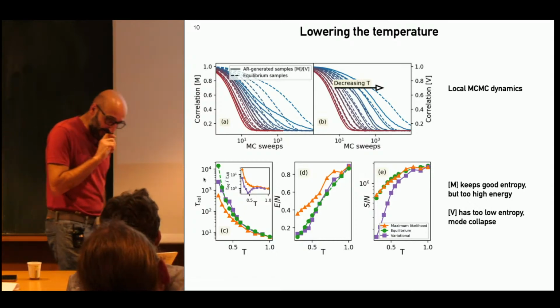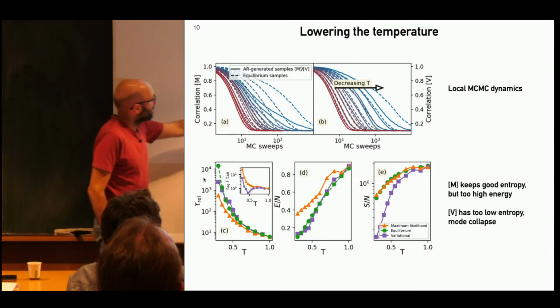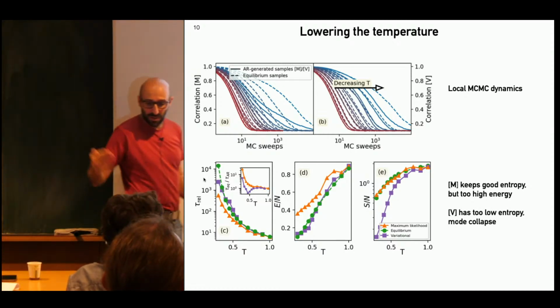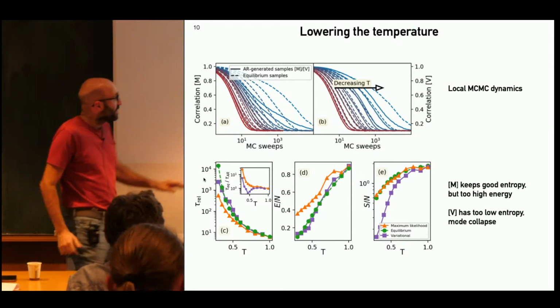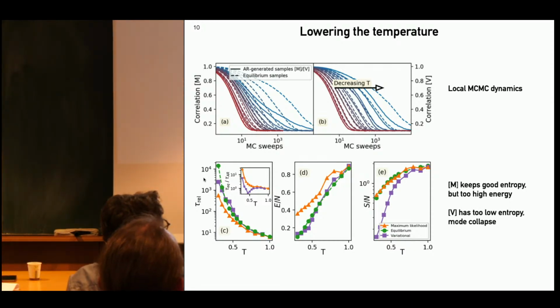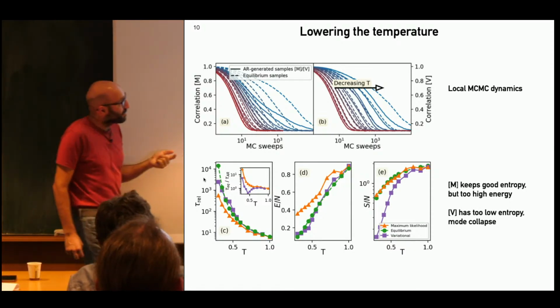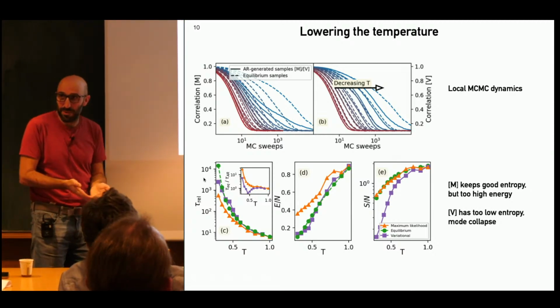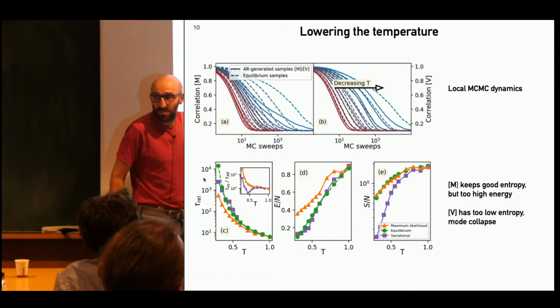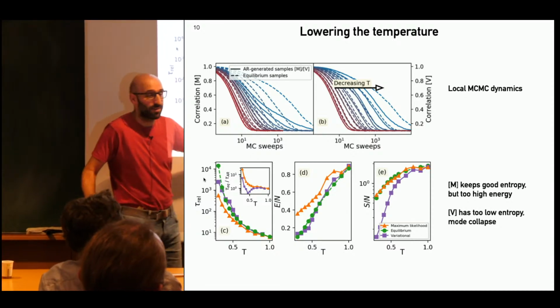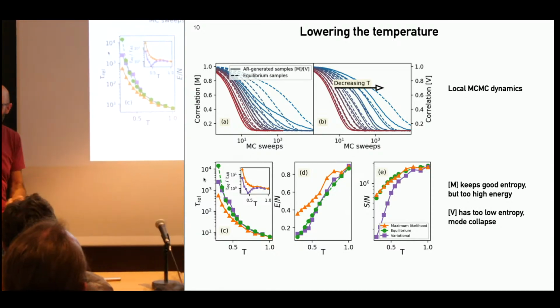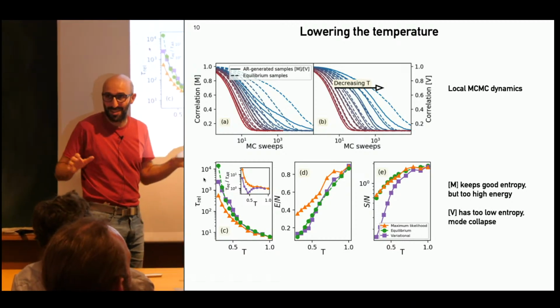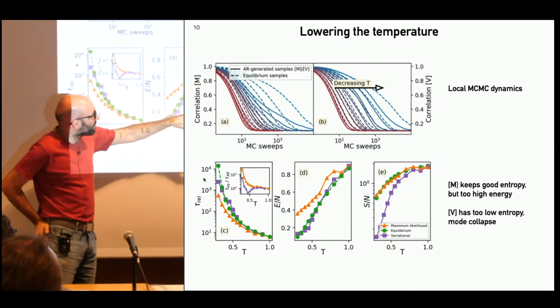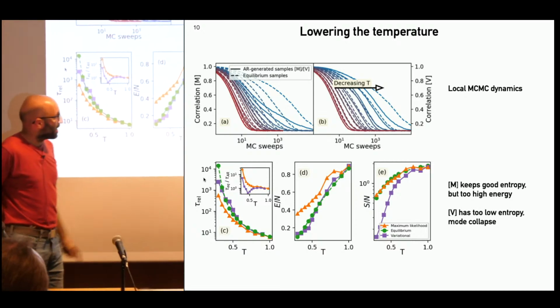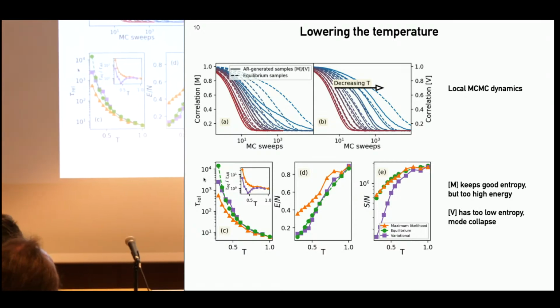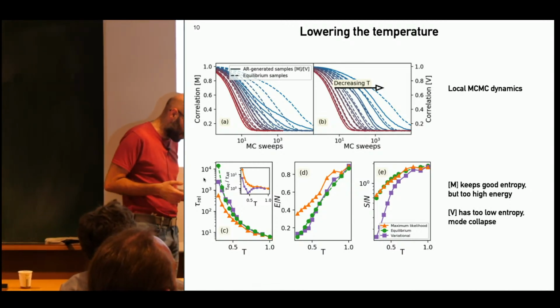Now, what happens when we lower the temperature? Here you have the energy and the entropy of these two models. What I'm doing here is lowering the temperature. For the maximum likelihood model, which is the orange, at each temperature I generate a new sample by local MCMC, because the temperature is still not too low, so I can still do local MCMC. And at each temperature, I relearn the model on the sample. That's the ideal setting; that's the best I can do. In the other case, the purple one, I'm doing the variational training, using the reversed Kullback-Leibler. In that case, I don't have to sample from the model.